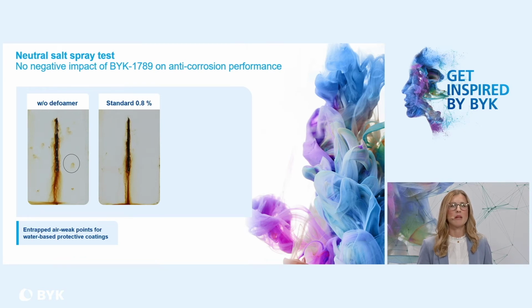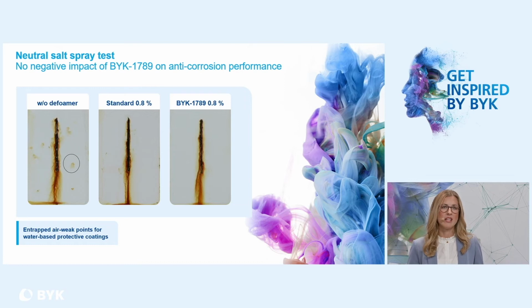The results of the electrochemical impedance spectroscopy match the results obtained by conventional corrosion test methods, such as the neutral salt spray test. Here, the sample without defoamer and also a standard defoamer show blistering and also some rust dots on the surface of the coating, whereas BYK-1789 defoams perfectly and therefore really improves the corrosion resistance of the coating. So these results show the specific need of a defoamer that is able to defoam or to release the foam in coatings that are applied in thick layers.